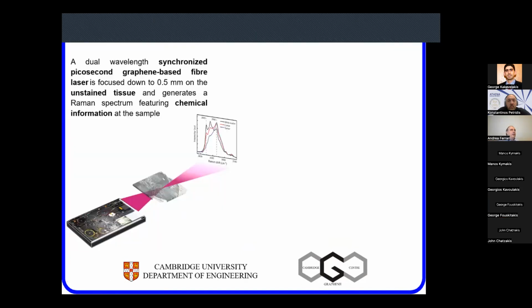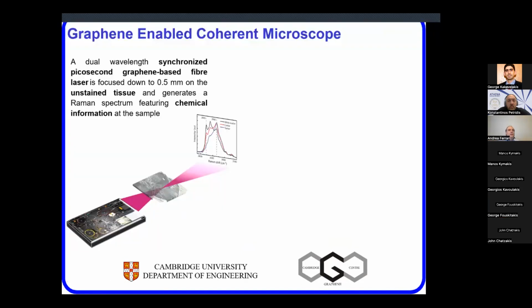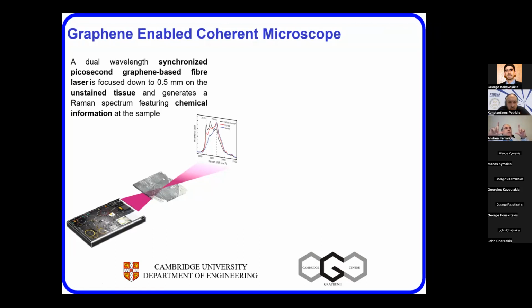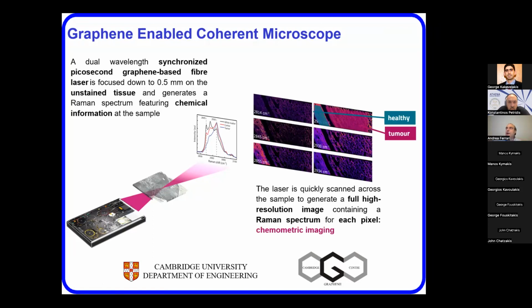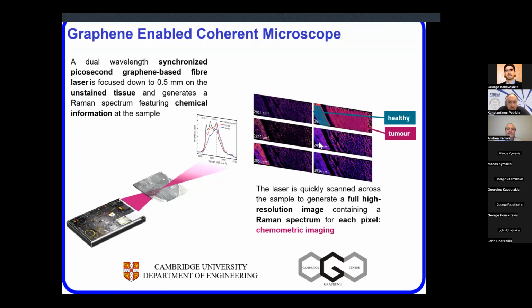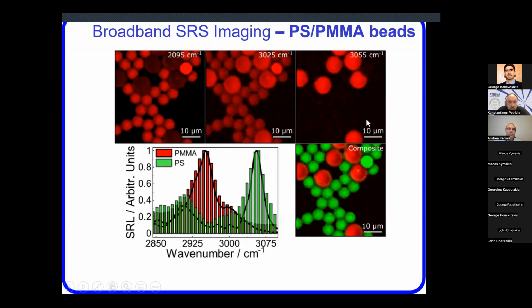So that was not expected in the experiment, but this is key because this synchronized emission is what you need to create a coherent Raman microscope. So then now we can put all of it in a shoebox, literally this size, no optical table, nothing. And the huge system that costs €1 million can be made much, much cheaper, much smaller, much lighter. And this can now be used for Raman imaging. And for example, you see here Raman maps, and they can distinguish healthy and tumor tissue.